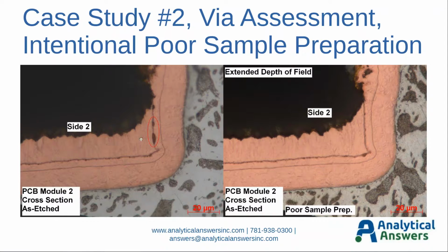And this is a type of defect that I would find while doing the assessment at the laboratory that I was working at, and then traveling out to the PCB manufacturer. We would prepare the same samples using their methodology, and I would then prepare them on their equipment using my methodology, and we would examine them side by side. And in almost every case, we would see that these particular defects or anomalies would show up in the samples that we had prepared using the methodology that I recommended, and they would either be masked or hidden by the methodology that they were previously using.